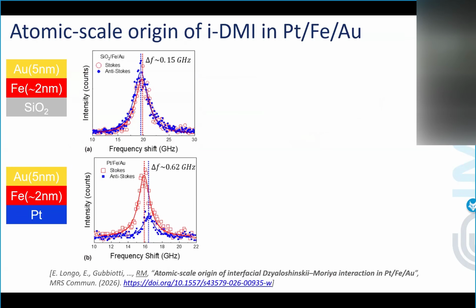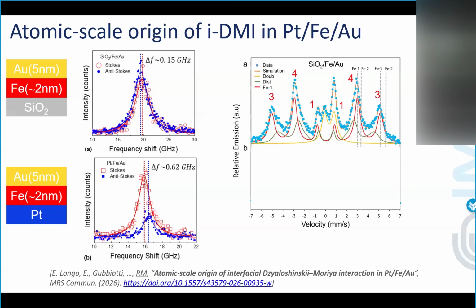Gianluca Gubbiotti was doing the Brillouin scattering in these two samples. You see the iron here was quite thick, 2 nanometers. We didn't expect to see Dzyaloshinskii-Moriya interaction. Actually, we didn't want to look for skyrmions, so it was totally another reason why we did that. But very interestingly, we find that there is a shift in the BLS spectrum when your iron is on top of platinum, but still quite thick, around 2 nanometers. And in order to understand the origin for this Dzyaloshinskii-Moriya interaction, we went to our Mössbauer setup.